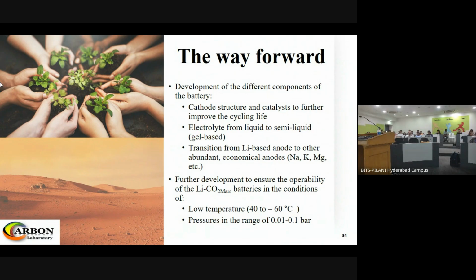And also we are looking into the low temperature region. And not only that, we are also interested in looking into the pressure, because at Martian conditions, the pressure is 0.01 to 0.1 bar. So again, the chemistry which we are trying to establish in the Earth atmosphere may not be valid. The same reaction pathways may not happen when we go to the reduced temperature region.